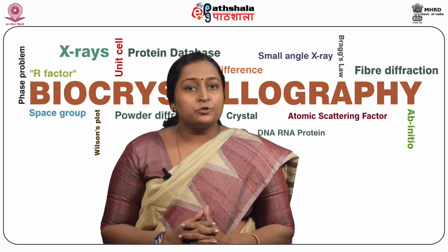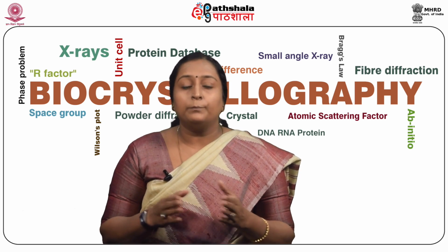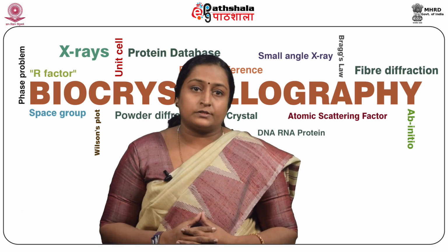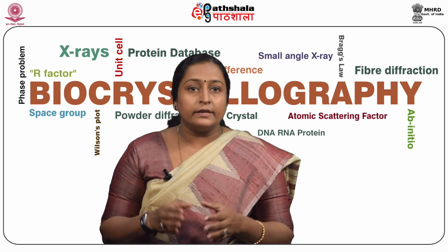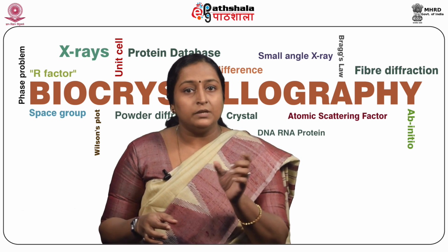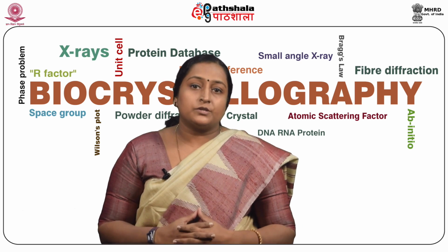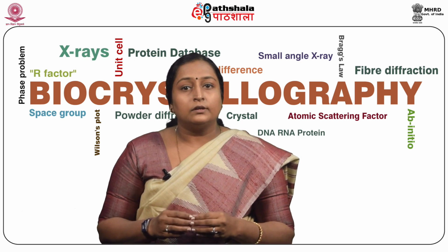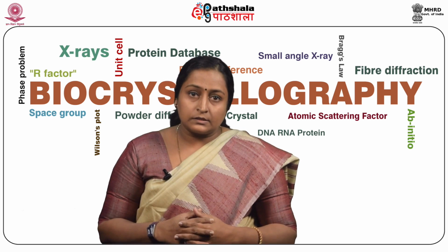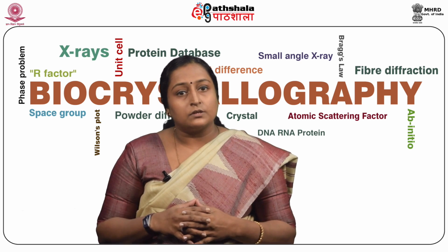B factor distribution plot is a very useful tool that prevents improperly set B factor cutoffs. Refinement programs depend largely on the B factor as a means to correct other problems that are not parameterized in the model, and the individual B factors also absorb scaling anomalies, uncorrected anisotropy, and other similar problems.